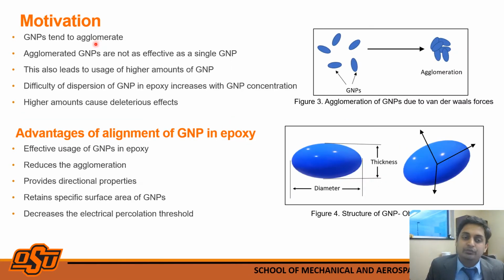The major drawback of using graphene nanoplatelets is their natural tendency to agglomerate. In figure 3, you can see separately spaced graphene nanoplatelets that tend to agglomerate because of van der Waals forces, forming a lump of particles. These lumps of particles are not as effective as single graphene nanoplatelets, which provokes the use of higher amounts of GNP to obtain suitable properties. But ultimately this gives rise to dispersion problems in epoxy and also causes some negative effects.